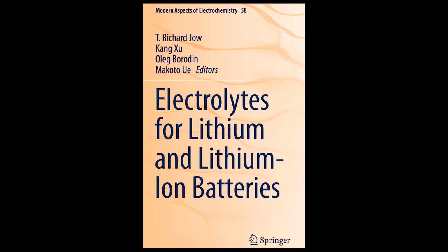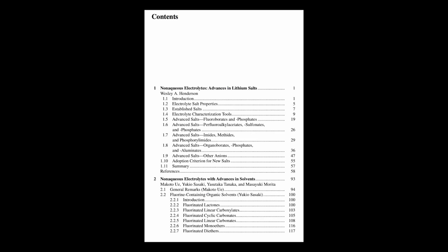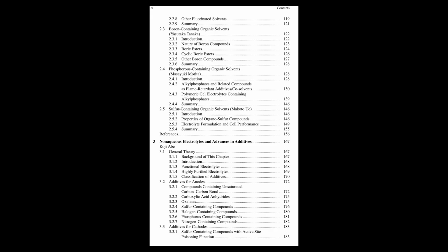The chapter then discusses cyclic carboxylic acid anhydrides, like succinic anhydride and maleic anhydride, discovered by Mitsubishi Chemical in 1999. Complex names. Yeah. These were found to be effective at preventing the breakdown of a specific solvent, propylene carbonate, PC, when used with graphite anodes. PC is a good solvent in some ways, but it can cause graphite to exfoliate, basically fall apart, so these anhydrides help to prevent that specific problem. Got it. Solving specific solvent-electrode interactions.